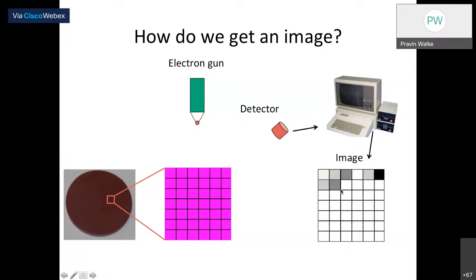These pixels are really very small, depending on the size of your electron beam, right? And keep in mind, the resolution of any SEM depends highly on the spot size. Later we use different software to analyze it, but usually the resolution will not be better than the beam spot size. So one has to really work on the spot size. If the spot size is reduced, then we will probably have very good resolution of the system.